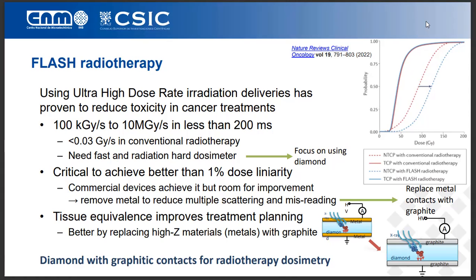So you need a fast and radiation hard dosimeter. In this case, as I mentioned earlier, we focus on using diamond. It is critical to achieve better than 1% dose linearity. This is a requirement for clinical applications. Commercial devices already achieve that, but I think there might be some room for improvement by removing the metal, to reduce the metallic electrode and the multiple scattering from the metal. By removing the metal and replacing it with graphite, which is the main idea, you also improve on the tissue equivalence, because you're removing a high atomic mass material from the device. Yeah, the goal is to get the diamond with graphitic contacts for radiotherapy dosimetry.